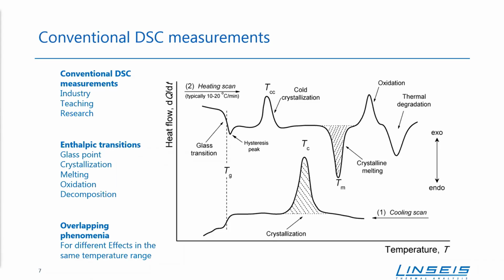And of course, again, the Tg, so the glass transition in this case. The DSC takes care of the enthalpic transitions, so we need any enthalpic change here to see any signal. Sometimes there are overlapping transitions like double peaks, or for example, the glass transition with the relaxation peak at the beginning of the first measurement curve. And so for different transitions, sometimes we need different sensors or different conditions for the measurement cell.